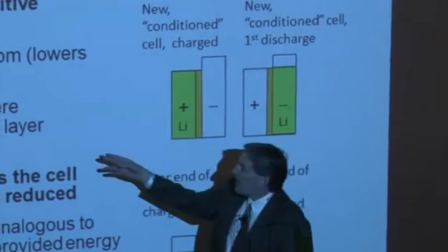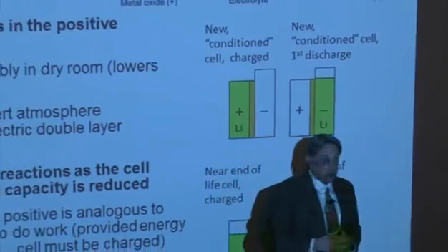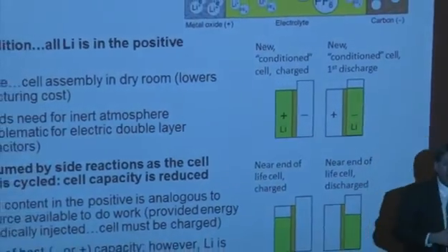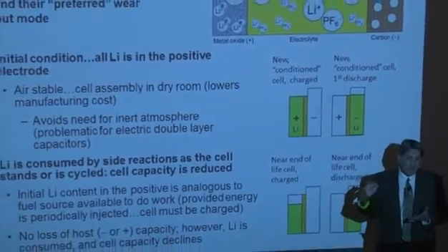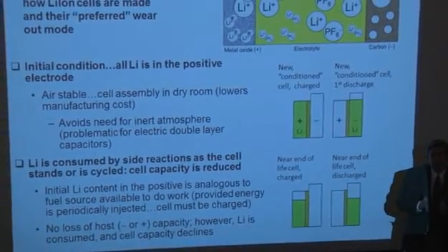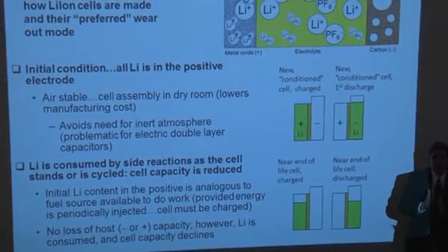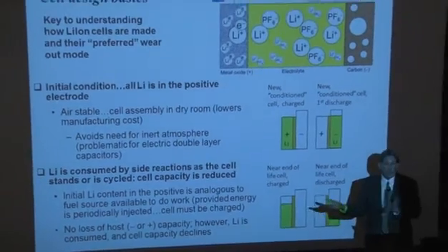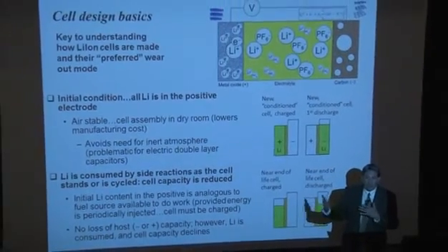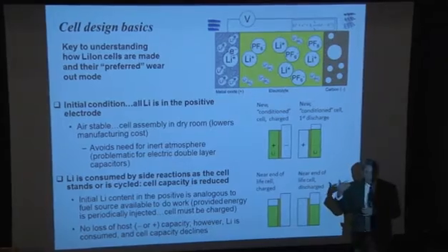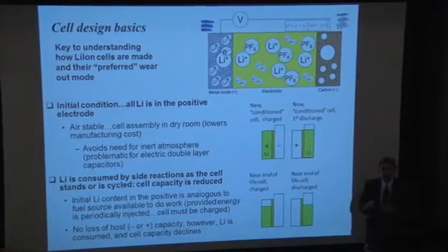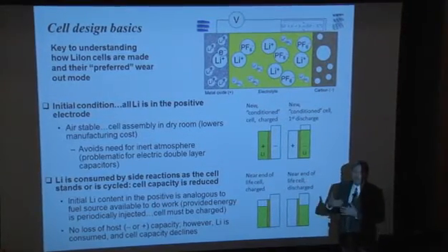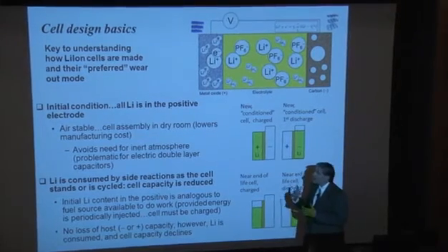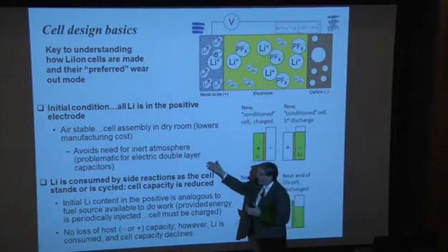That's important. I make the note here about double-layer capacitors. A lot of people thought we'd be using more electric double-layer capacitors than we are today. One of the big problems there is they have to be hermetically sealed, just like lithium-ion batteries, but they also have to be assembled in an argon or inert atmosphere, and that's proven to be very expensive. So even though the raw materials, carbon, are cheap, although they have to be prepared and etched at high temperature and cleaned, the assembly process is extremely difficult in that inert environment, and it's been one of the limiting issues for that technology to go mainstream.